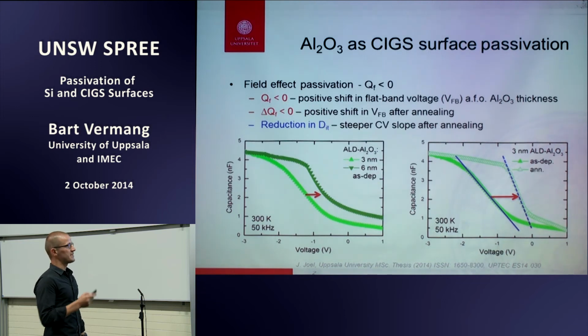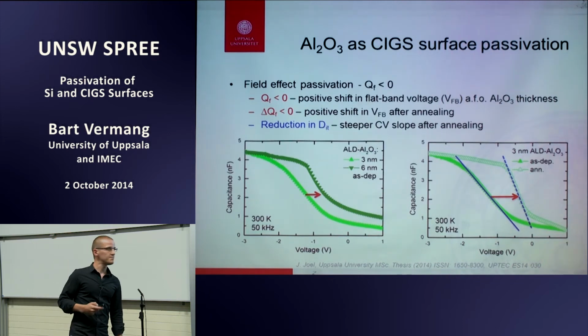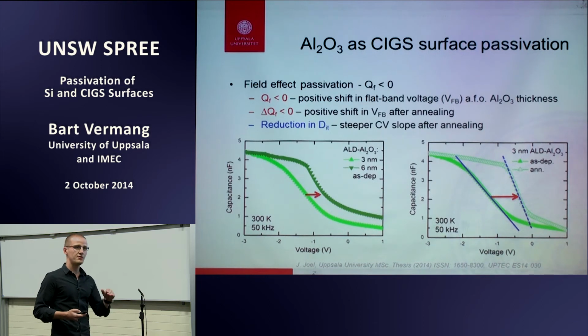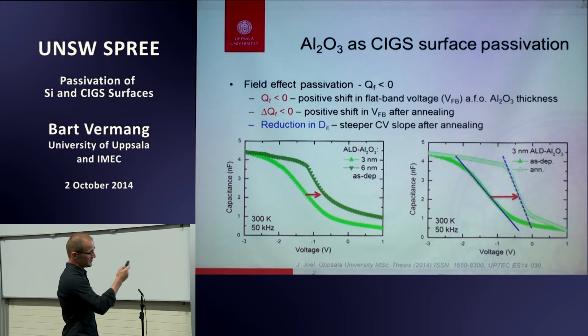There you go, from as-deposited to annealed ALD aluminum oxide passivation layers. Annealed is more honest. It's mimicking the solar cell process because we are growing the CIGS layer on top of the aluminum oxide, not vice versa. You see the same thing again.